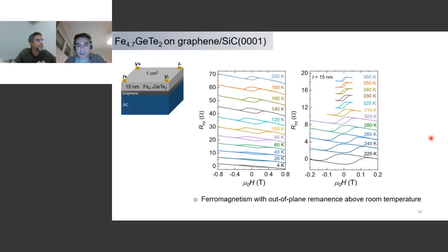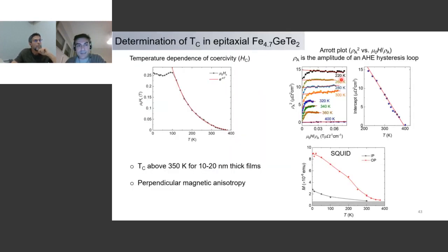The most important practical thing here is that we do see an increase in the Curie temperature. So it goes beyond room temperature. Even at 360 Kelvin, we still see the anomalous Hall effect, which is proof that the material is still ferromagnetic. We confirm that, for instance, by doing SQUID measurements, so magnetometry. And again, we see that magnetization remains beyond room temperature. And in this case, we prove that it has a perpendicular magnetic anisotropy. That means the spins are aligned out of plane preferentially.